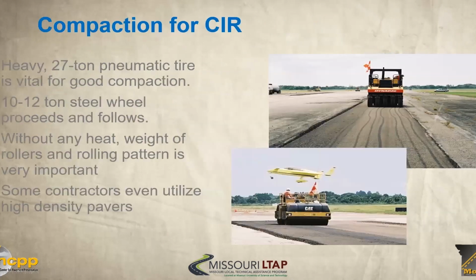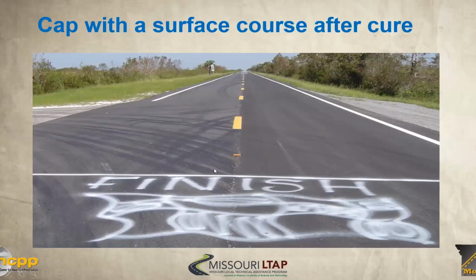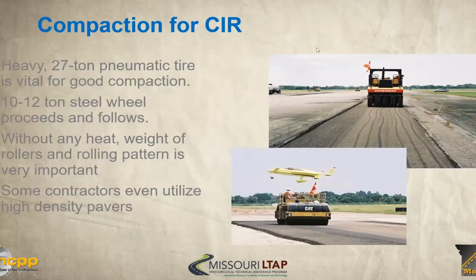So again, compaction is key. We have the need for a big pneumatic tire roller because we're compacting thicker lifts, and then you've got the preceding and following steel wheel. Without heat, the weight of the rollers and the rolling pattern is very critical. Some contractors even utilize high density pavers that are getting compaction behind the actual screed, which is pretty interesting as well. And it's always capped with the surface course. After the base material cures, we do leave this base material open while the moisture evaporates out of the mix.